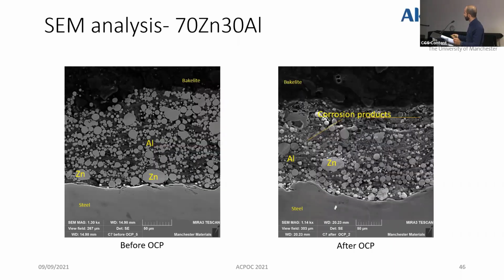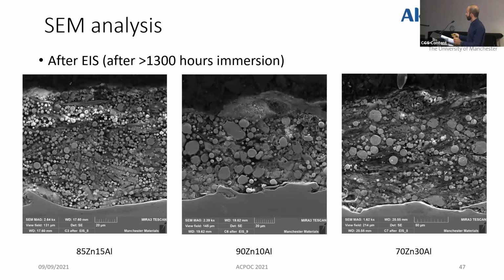The same one here, but as you can see, for a high amount of zinc and a high amount of aluminum, most of the zinc particles in contact with the steel substrate are not that consumed, only the first part here. And I think this is because the aluminum particles or aluminum flakes are passive and have no chance to activate and just disconnect between these zinc particles. After more than, actually I think, 1300 hours, you can see the steel substrate is still not affected, and the corrosion products are accumulated inside the coatings.